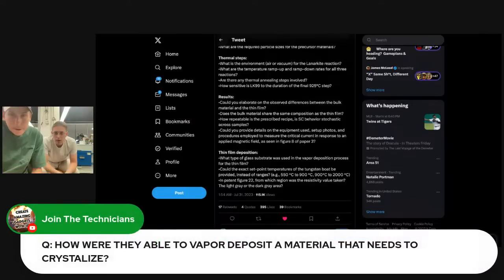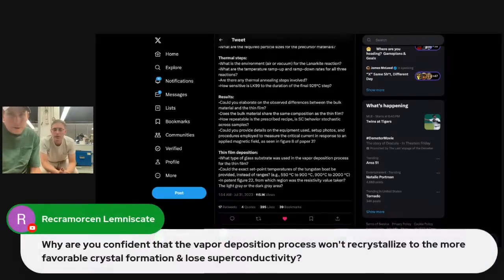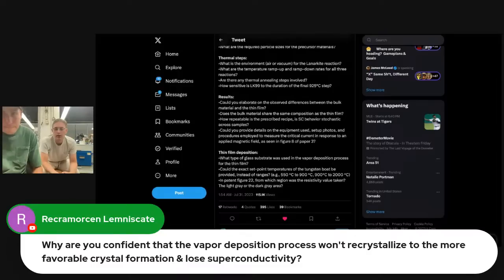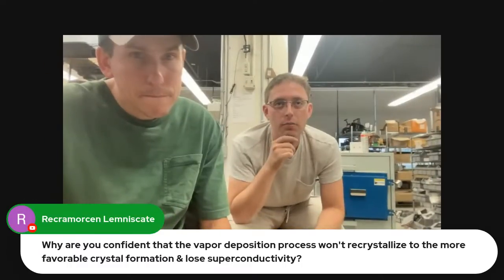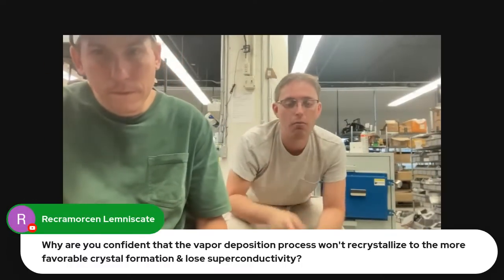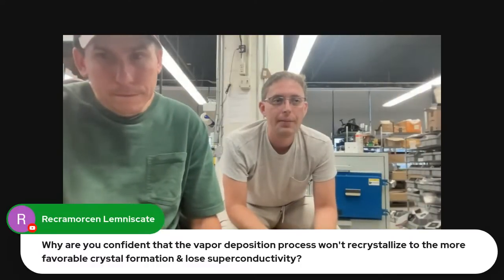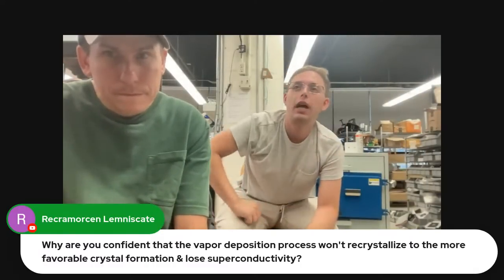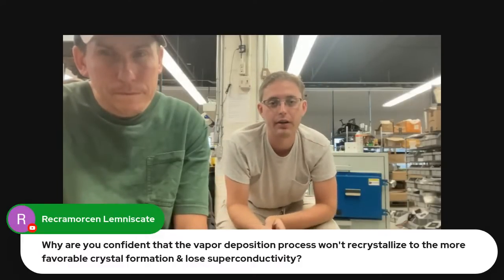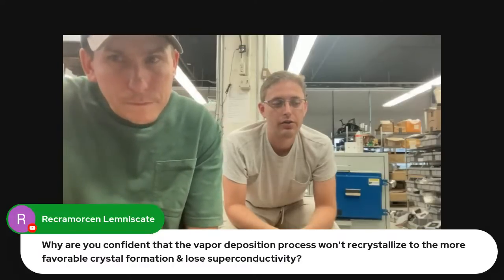Why are you confident vapor deposition works? I'm confident vapor deposition would work because if you deposit onto lanarkite specifically, it will nucleate crystal growth. What's happening in the crucible is the copper phosphide is decomposing and the phosphorus is contacting the lanarkite surface from the vapor phase, and it's reacting with the lanarkite to replace some of it, and that starts the crystal growth nucleation. And within those temperature ranges, oxypyromorphite is a liquid, or at least this phase of oxypyromorphite that's heavily copper doped is a liquid, and that liquid will form on the surface of the lanarkite, and the lanarkite should induce the crystallization of the phase that we want.